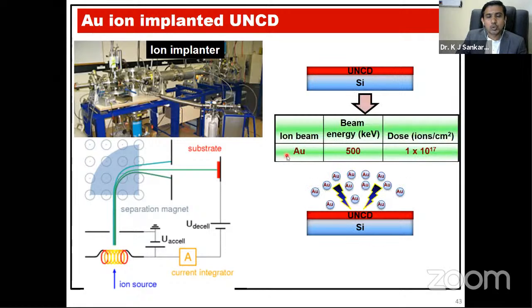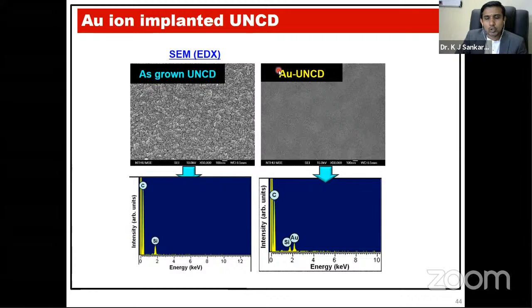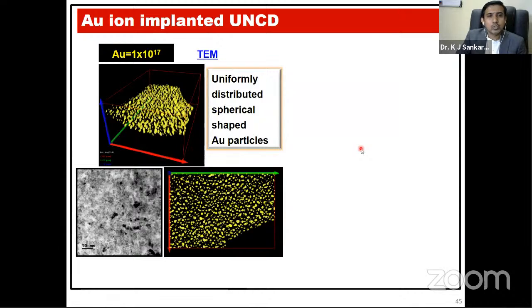Then we used a gold ion beam of 500 keV with a dosage of 10^17, and these gold ions are implanted on the UNCD, forming UNCD with gold. So this is the UNCD implanted with gold ions, and you can see from the SEM EDAX the presence of gold. But for the as-grown UNCD, there is only the presence of silicon, because we grow the UNCD on silicon substrates.